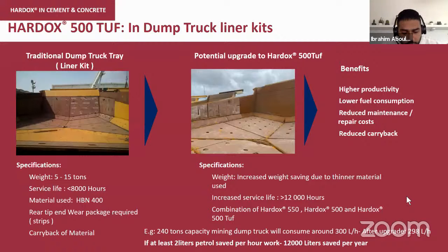One also case from one customer that we have, in that case, they also had their own liner kit. They are using 400 Brinell wear plate, and the weight of the whole liners was between 5 to 15 tons. They have service life less than 8,000 hours. And again, they came to SSAB, how can we improve our performance? How can we improve the productivity? Hardox 500 Tough is the answer, with some additions of 500 and 550, depending on what is the use. We increase the productivity by around 12,000 hours. So we have from 8,000 hours to 12,000 hours service life, as well as using thinner material when upgrading to higher grades allowed us to decrease the weight of the liners and the whole truck, of course.